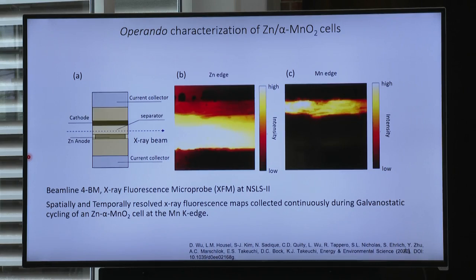So this was actually a collaboration between Ken Takeuchi and David Bock, who's a Brookhaven scientist, to design an operando cell, and I'm showing it as a little cylinder, and what you can see is that it's stacked. So we've got the cathode on top with a current collector, we've got a separator in between, and then we've got the zinc anode on the bottom. And what we're doing is X-ray fluorescence mapping. So that means we're looking for a specific element. And if you look at the middle picture, everything that's bright means there's a lot of it present. And what we're doing is mapping zinc.